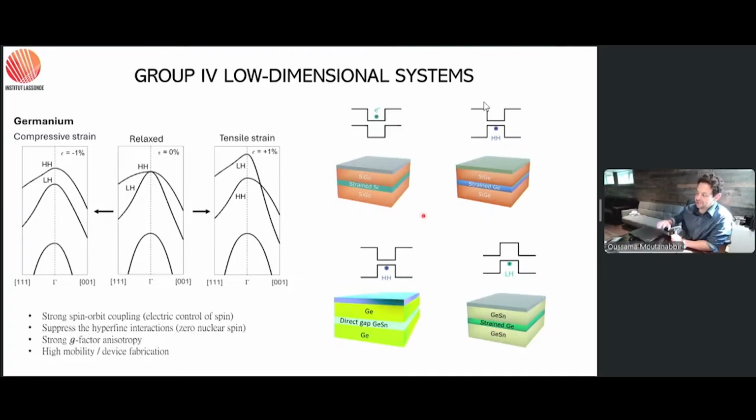Forget about the hole, which comes with a bunch of problems. Just electron spin, which is a well-engineered heterostructure. There's a lot of papers on this, a huge community. They are still struggling with getting rid of germanium because your electron wave function will reside at the interface. So a fraction of the wave function will feel the silicon germanium alloy, and in that alloy there is germanium-73, and that's a major factor. So there is this pressure in getting access to germanium isotope from American companies and labs.